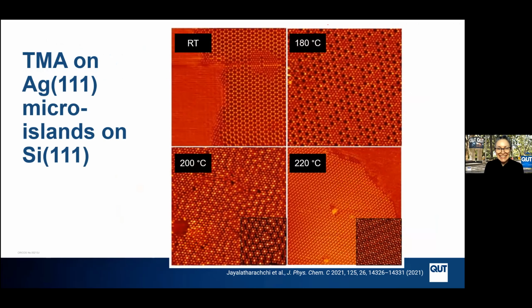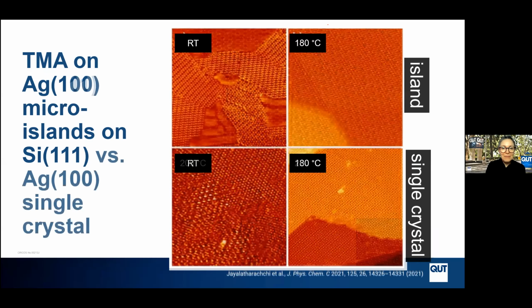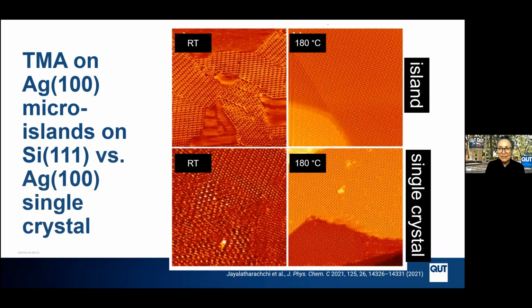So as we are wont to do, we then covered them with molecules. And as it turns out, they behave identically to the large single crystal substrates that we had been working on. So this is interesting. It's a whole new approach to doing growth experiments rather than sputtering and annealing a single crystal. You can do a simple flash annealing of silicon with the deposition of silver, and you end up with a beautifully ordered set of silver crystallites to work on. So you can see here she was able to reproduce the same TMA work that we just looked at from a single crystal surface, and at the same time was able to study what the molecule does on the 100 facets. Here there's less in the literature, so she also reproduced these experiments on a 100 single crystal.